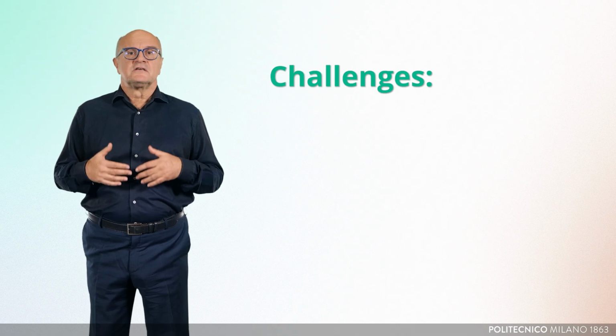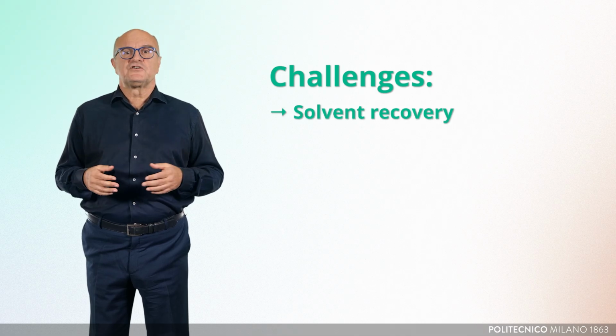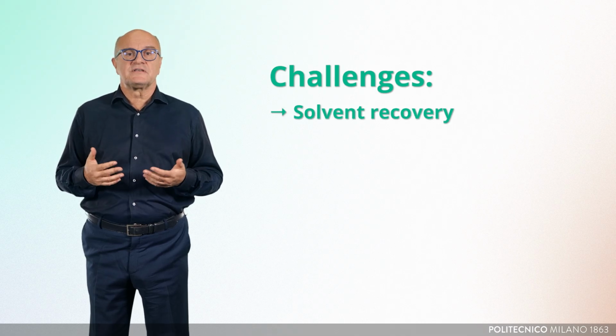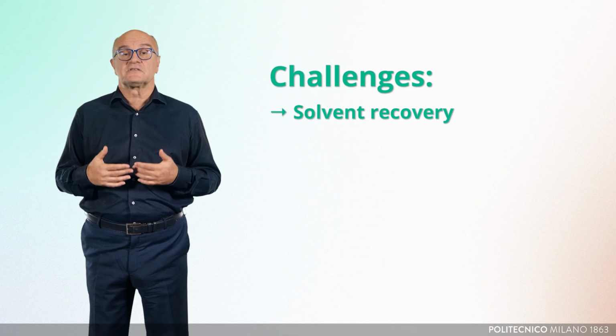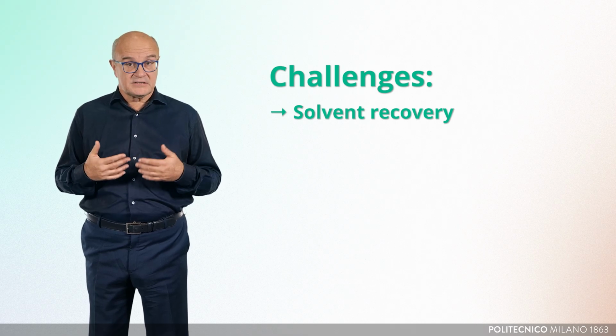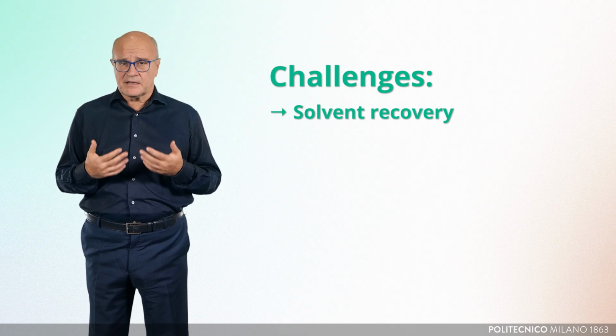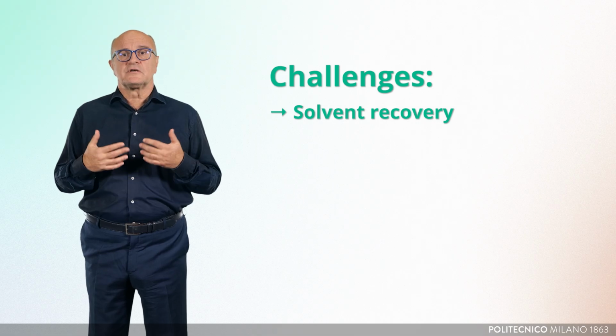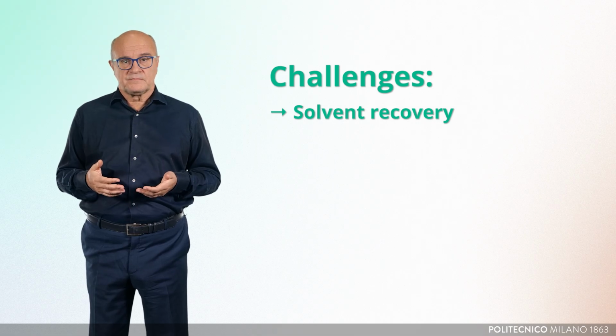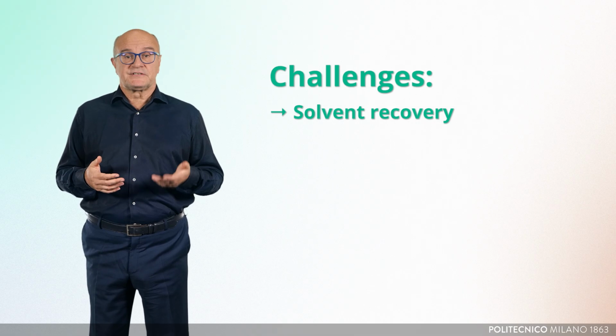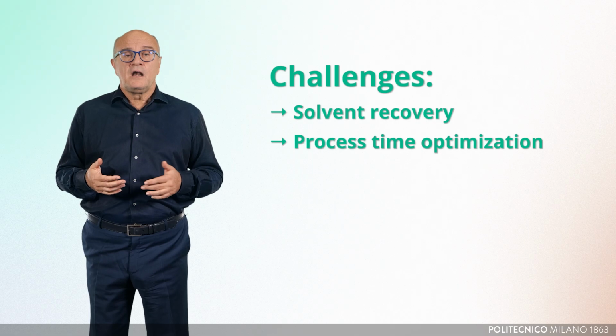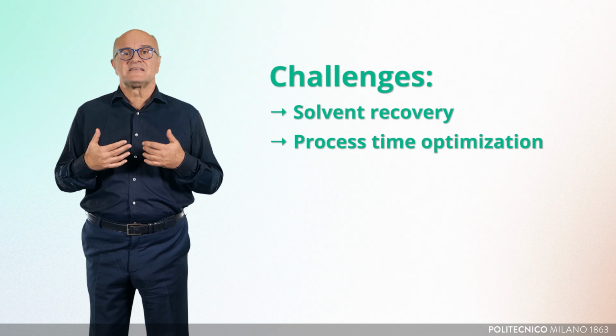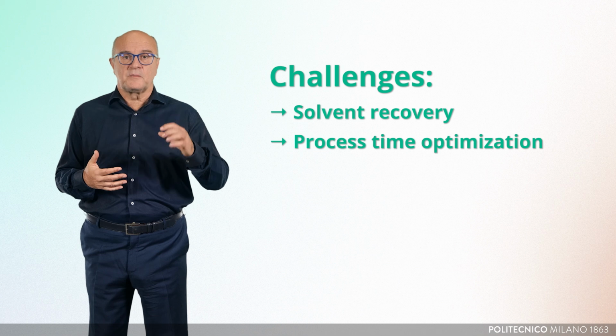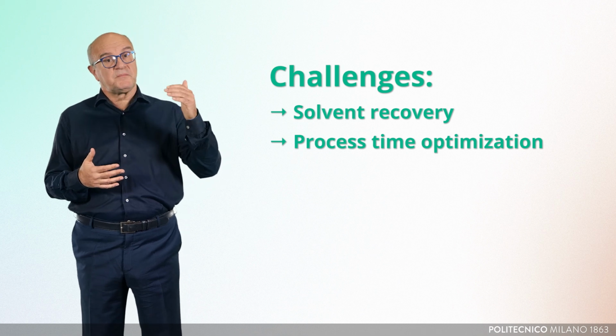While solvolysis is a promising technology, it is not without challenges. First, solvent recovery: efficient separation and reuse of solvents are needed to make the process economically viable and circular. And this can be a challenge when using complex solvent mixtures. Second, process time optimization. Long reaction times might be necessary in case of very thick composite parts and very high Tg polymer resins.